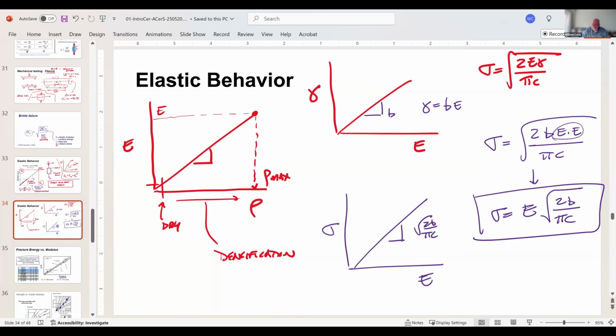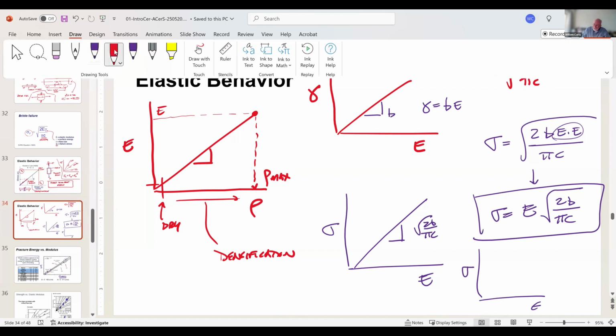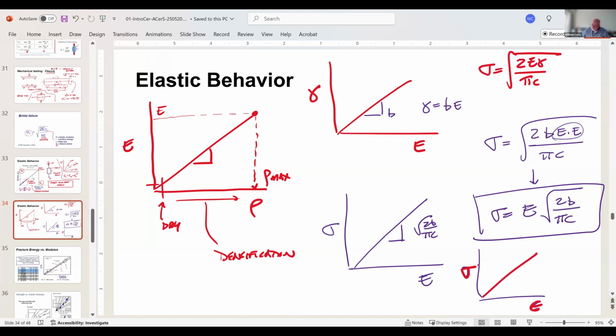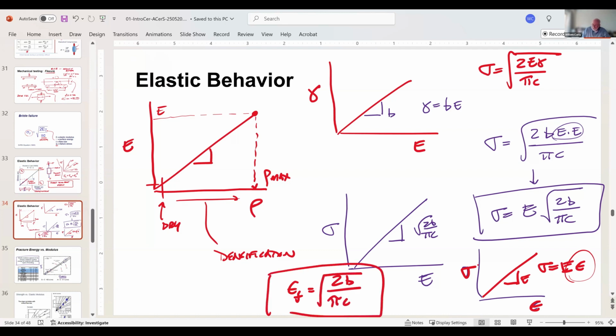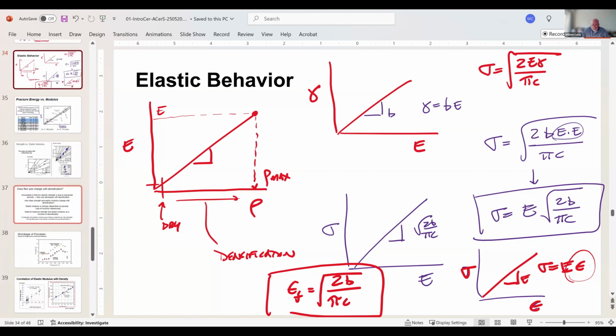Oh, no, wait a minute. If I go back to the previous slide here, I've got my strain, my stress. So stress, strain, elastic modulus. If I do this equation, I get sigma equal to E times strain. So now strain at failure is equal to the square root of 2B over pi c, if my strength value scales with elastic modulus, which also scales with density. This means that I have one flaw population in my system if my strength scales with elastic modulus. So we tested that idea, and we came up with samples from industry.